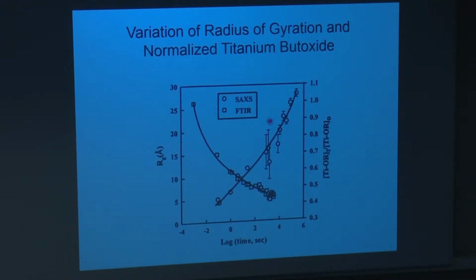And this slide just shows what happens if you look at the FTIR data for the alkoxy groups and how they decrease over time. And then you look at the radius of gyration from data you get from small-angle X-ray scattering. What you see is these particles start growing very quickly. So using this particular technique, you should be able to get a better picture of the hydrolysis and condensation kinetics for these particular systems.